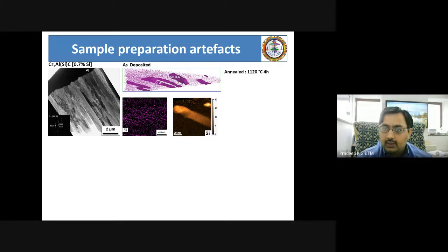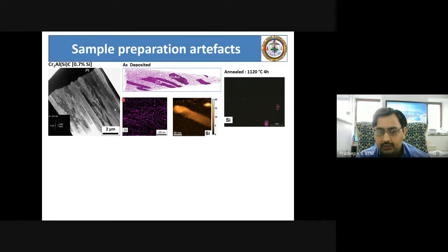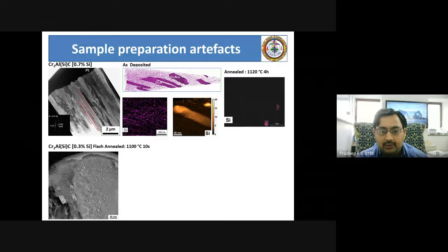This means when you look at this in a three-dimensional form, you see something. When you look at this in a projected two-dimensional form, you don't see many things. And this is because these regions, what you see here, where there's a bright contrast, are responsible for the disappearance of these kind of precipitates sitting on a grain boundary, which is a defect, because the sample preparation or the FIB-induced sample preparation can smear away all this information or remove these precipitates preferentially from their ideal location. So these are called artifacts in microscopy, where some nanoscale feature disappears because of the preparation-induced damage or because of the imaging-induced loss or something that can happen during the imaging process. Therefore, some of this vital information on the microstructure and phase evolution can be missed in these materials.